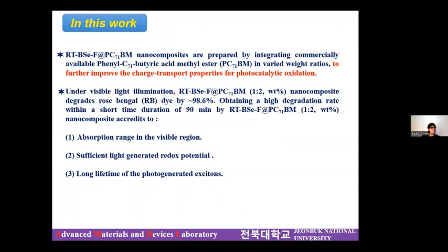In this work, we first synthesized the organic molecule and named it RT-BSe-F. After that, we made nanocomposites with the PCBM material. As we all know, PCBM acts as an electron acceptor, and we made these composite materials in different configurations, for example, 1:2, 1:3, and more. We found that when we used a specific concentration of this composite material, it showed degradation of the rose Bengal dye up to 98.6%, which is very promising, and that too in a very short duration of time, for example, just 90 minutes.